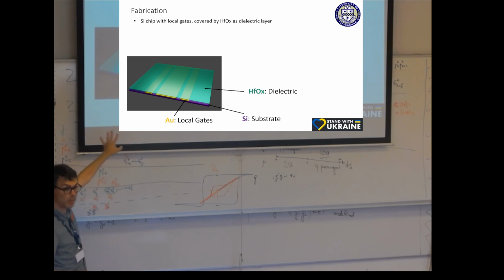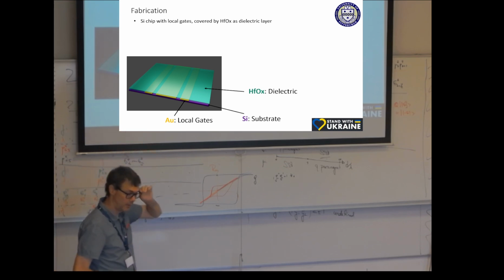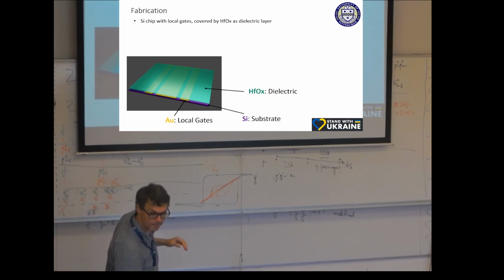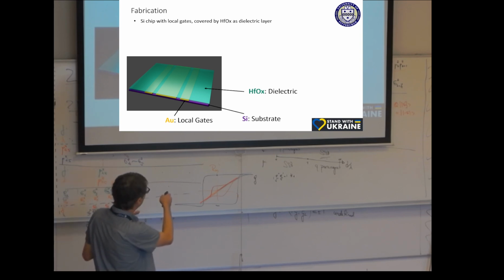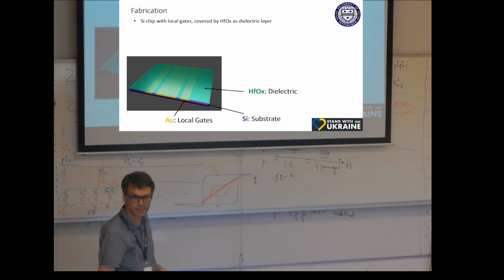So this is just the preparation. Why do you use hafnium oxide? It's a very high quality dielectric with a dielectric constant could be 20 or so. So it transfers electric field through very efficiently. And it's a very low defect, high breakdown voltage dielectric. It's a very convenient dielectric.